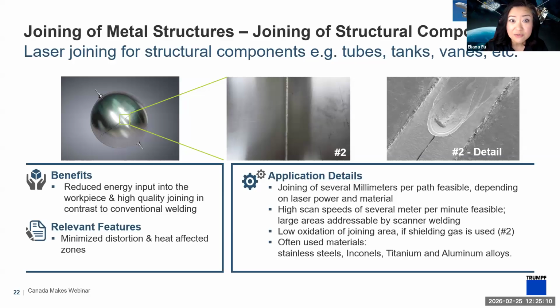So you can move relatively fast. So again, you're improving your throughput. So whatever meters per minute that you use. And you can have a large area addressable by using a scanner for your welding as well. Another benefit, if you use shielding gas, is to keep the oxidation of the molten area down. So this is very helpful for things like titanium, which is very susceptible to oxidation in the molten state, and other materials like aluminium, Inconels, so nickel alloys, and stainless steels.